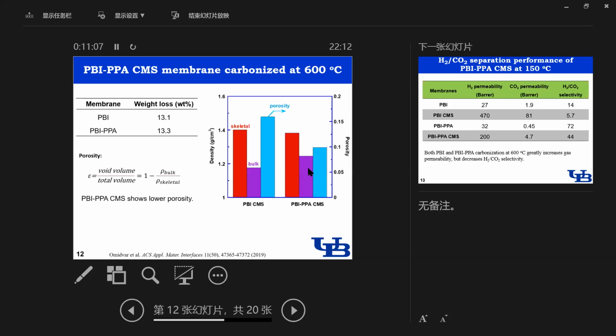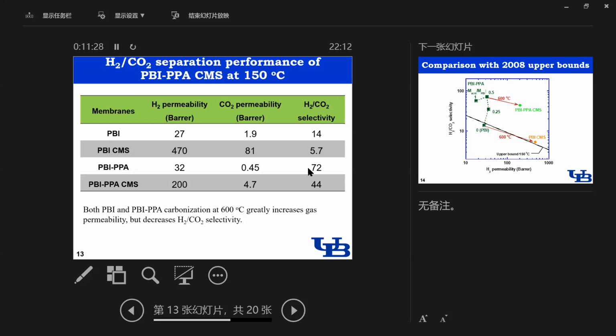And then we tested skeletal density and also bulk density of PBI CMS and PBI PPA CMS, and we find that compared to the PBI CMS, PBI PPA CMS shows lower porosity. And then we also tested pure gas hydrogen CO2 separation performance of all CMS at 150 degrees C. So firstly, for both PBI and PBI PPA, hydrogen permeability and gas permeability increase after carbonization, but with a loss of hydrogen CO2 selectivity. And compared with pure PBI CMS, PBI PPA CMS shows a little lower hydrogen permeability but higher hydrogen CO2 selectivity.